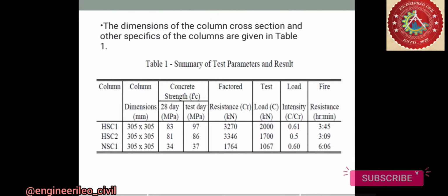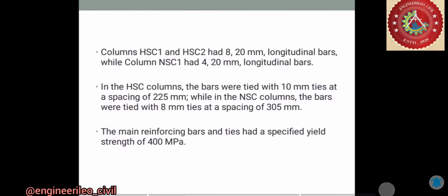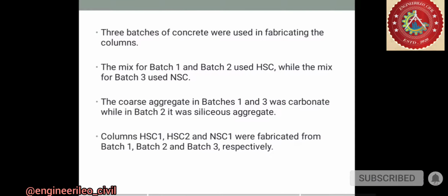Here he has taken two high strength concrete columns with 8 20 mm longitudinal bars and a normal strength column with 4 20 mm longitudinal bars. In the high strength columns it is 10 mm ties at 225 mm spacing. In the normal strength column it is 8 mm ties at spacing 305 mm, and the mix is of batch 1, batch 2, batch 3, where batch 1 and batch 2 are high strength, and batch 3 is normal strength.